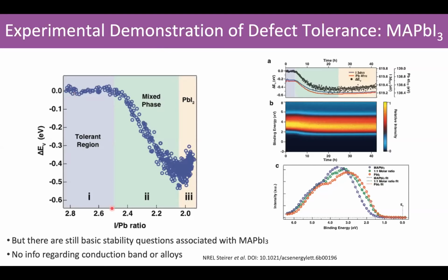And it's not until we get to 2.5 that we actually start seeing a clear difference in the valence band edge of the material. In other words, we're creating lots and lots of defects as we're changing the composition here, but it's just not doing anything to one of the key functional properties.